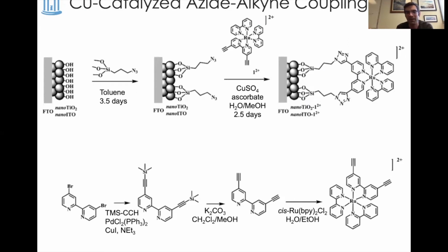And stabilization was a huge challenge because we wanted to work in water, and ideally water at pH 7 or even more basic. And so one of the many strategies that have been taken to try to enhance the stability was to go from phosphonate to silane linkages. The problem is that the silanes tend to be pretty reactive. Synthesizing the catalyst with pendant silanes was often problematic, and you'd have hydrolysis or side reactions,